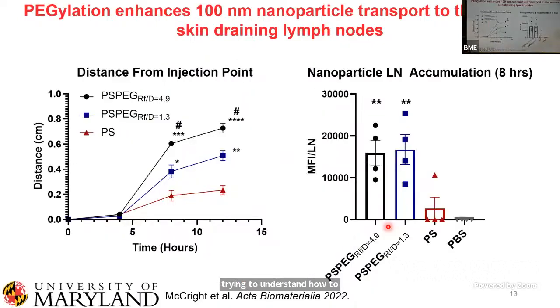And so we sought to quantify that because, of course, it's one thing to have an image. It's another thing to actually have some sort of quantitative analysis of what's going on here. And so we did both the distance from the injection point, so how far did the particles get, and then also the accumulation of the particles in the lymph node. And so you could see that in terms of distance from the injection point, our densely PEGylated particles traveled the furthest.